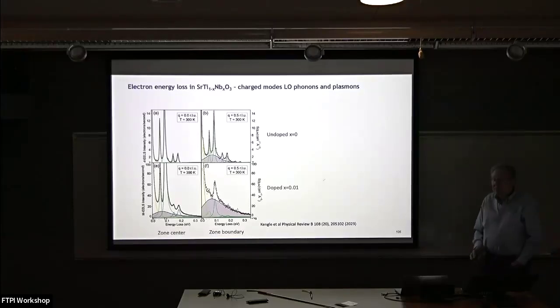If you go down, however, what you should have seen, and what you would have seen, by the way, if you did this experiment in gallium arsenide, is an LO phonon and a plasmon, with a very sharp excitation. They're both longitudinal modes. They hybridize, and you get an in-phase and an out-of-phase mode. But that isn't what you see at all. You see a bump. And by the way, the bump has the same spectrum as this bump. And then, when you go to the zone boundary, this bump just gets bigger. And by the way, the oscillator strength in here is roughly what you would have expected from the plasmon, except that it's completely and somehow mixed.